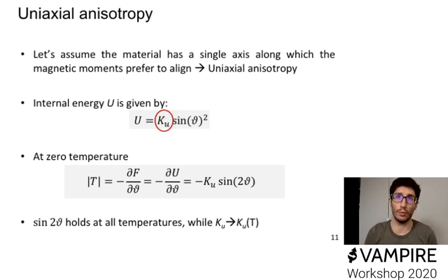Again, as I said before, usually the entropy contribution is not large, and it is possible to use these analytic relationships even at fairly high temperatures, accounting for the fact that as the temperature increases, the anisotropy will decrease, and it will anyway be more complicated to extract it. So the accuracy of the results usually will be slightly lower as we approach T_C.